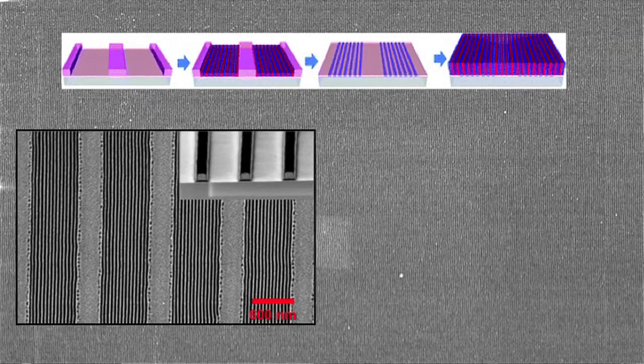A few years ago, my research group reported an interesting approach: block copolymer self-assembly can really enhance the pattern density of conventional photolithography. We can get less than 20nm scale patterns from a 100nm scale photolithography process, and we could also entirely transform micrometer scale photolithography patterns into nanoscale patterns based on this approach.